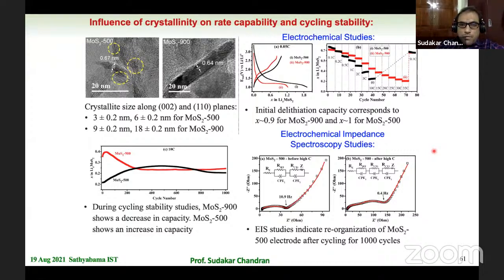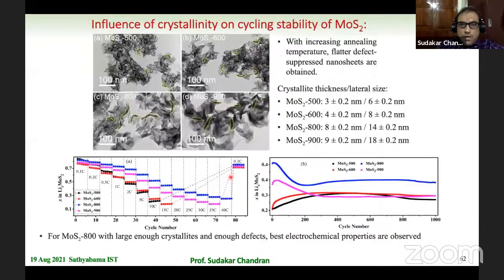The very complicated and intricate reorganization of molybdenum disulfide during the cycling is what makes the lithium capacity keep on changing. And therefore, these studies that we did systematically on a wide range of annealed samples, with different extents of defects, show that, in fact, one can control the cyclic stability as well as the rate capability.